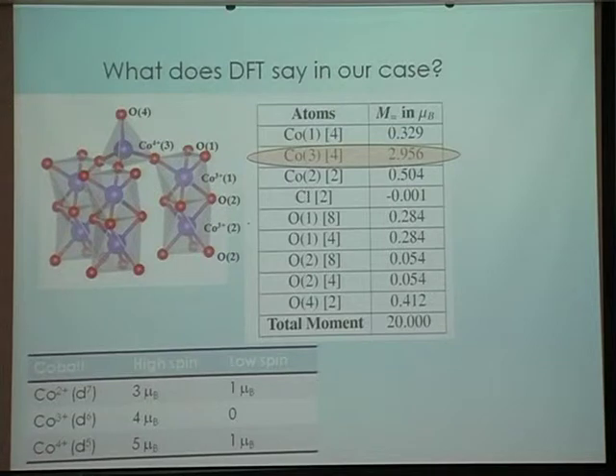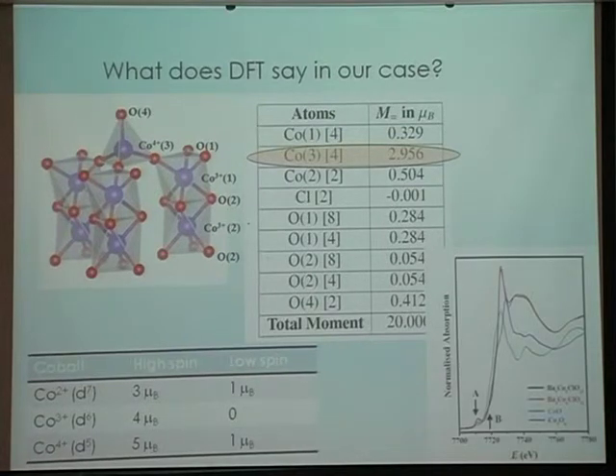So that's what happens. Then we did an X-ray absorption near-edge spectroscopy measurement on cobalt, this is the cobalt K edge, and this particular edge of cobalt in XANES is kind of a fingerprint of its oxidation state. You can see that the black and the red are the results from our compound, and the blue one is the result from Co3O4, a 2 plus 3 plus mixture that we know. And the edge matches quite well in energy. That essentially says that this calculation, which says this would be 2 plus and these would be something between 3 plus and 4 plus, looks quite true.